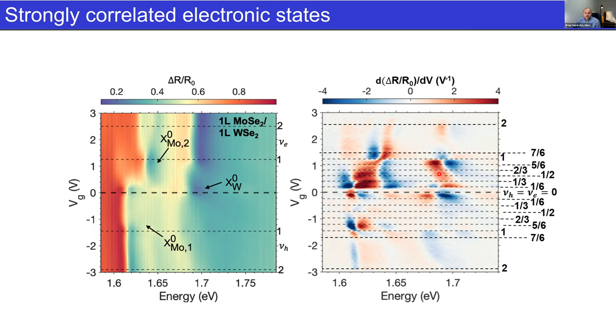And as well, we have the fractions of six in the Moiré lattice that sort of magically appear as well. So you can see, for instance, the 7/6 appears quite clearly. The 1/6, you can see this sort of sharp feature stop here, and so on. So we think we see signatures of these strongly correlated states at all of these different, there's a couple more, at all of these different fractional fillings.